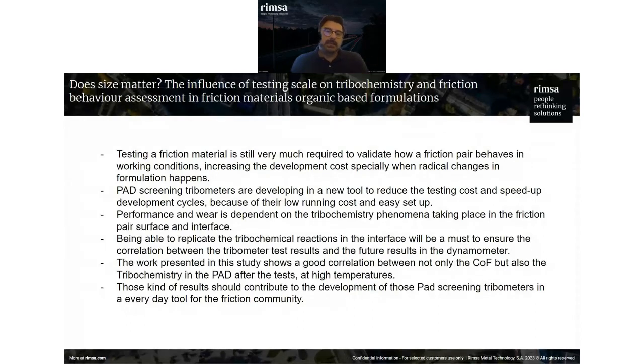And the work presented today in this study shows a good correlation between not only the coefficient of friction, and this is very important, the tribochemistry on the pad after the test at high temperatures. For us, it's very important to make sure to work with enough surface of friction material. In this case, we are using around 10 square centimeters to be able to achieve the temperature on the surface of the brake pad and the rotor, the same temperature only by friction that you achieve in a car or you achieve in a full scale dynamometer.